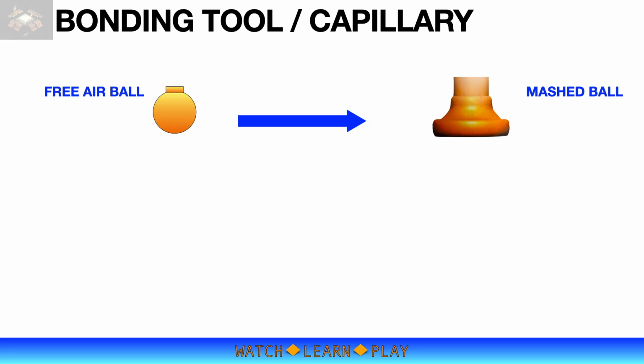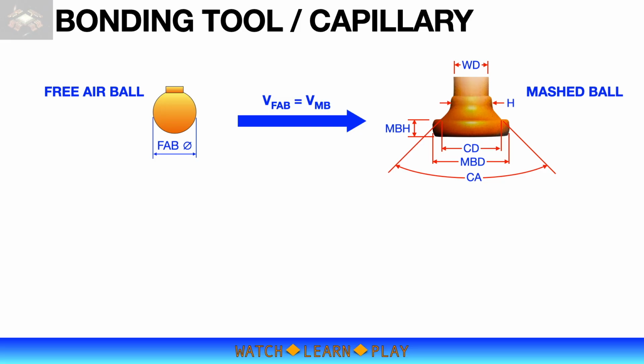Since bonding starts with the free air ball, how do we know the correct free air ball size to achieve the desired mash ball size? We know that the volume of free air ball is equal to the volume of mash ball. Mathematically, we can calculate the free air ball diameter using the dimensions of capillary, target size of mash ball, and wire diameter. H is the hole size of capillary, along with CA and CD. MBD and MBH are the target size of the mash ball, and WD is the wire diameter to use. The derived formula equates the volume of mash ball to the volume of free air ball.